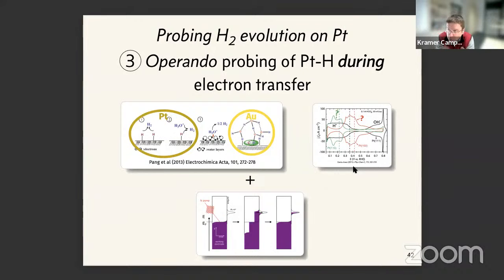So I told you that if we are going to do this experiment on platinum, we need to be able to probe the platinum hydrogen vibration, or platinum hydrogen structure. I showed you we can do this by probing platinum hydrogen vibration. We need to be able to also initiate charge transfer. I showed you we can do this by this 1 photon excitation and the detection of photocurrents.